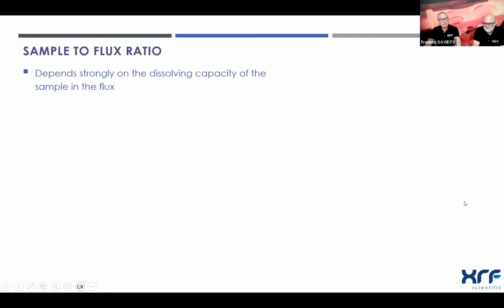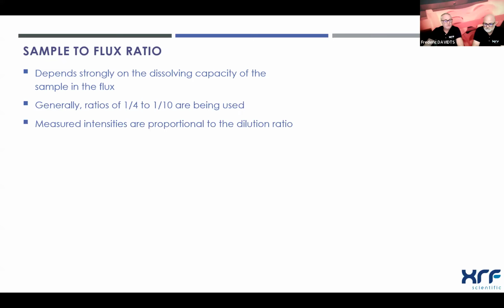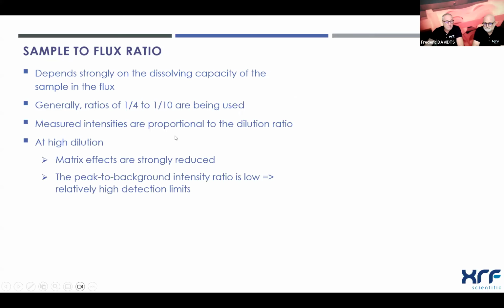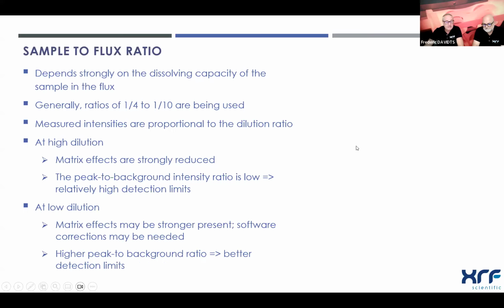The sample to flux ratio will depend strongly on the dissolving capacity of the sample in the flux. And generally, we are looking at a 1:4 to 1:10 dilution ratio. Of course, measured intensities are proportional to the dilution ratio. So what does this mean? When we have a high dilution, for example 1:10, then the matrix effects that may be present in the sample are strongly reduced. But on the other hand, the detection limits may be a bit higher because we have lower intensities.